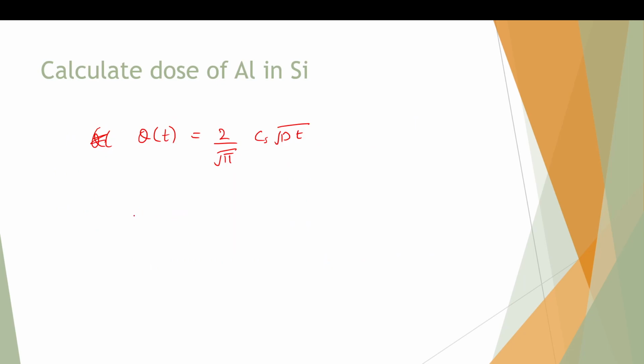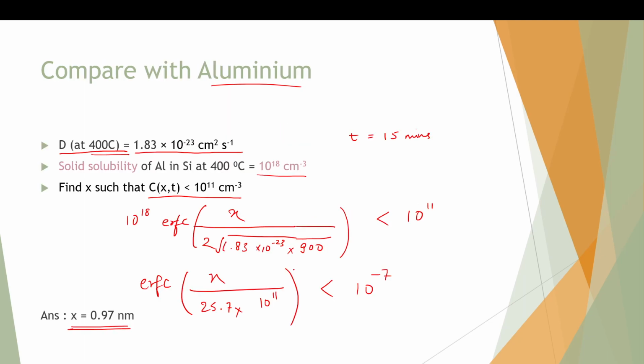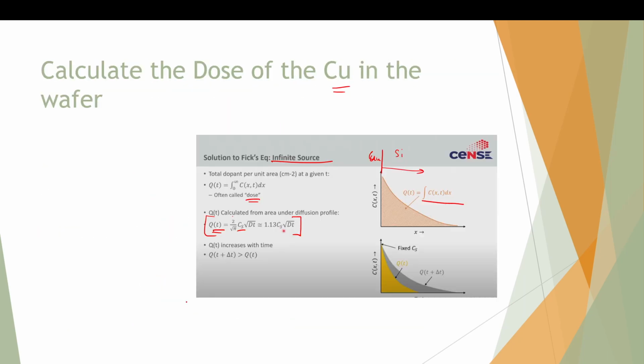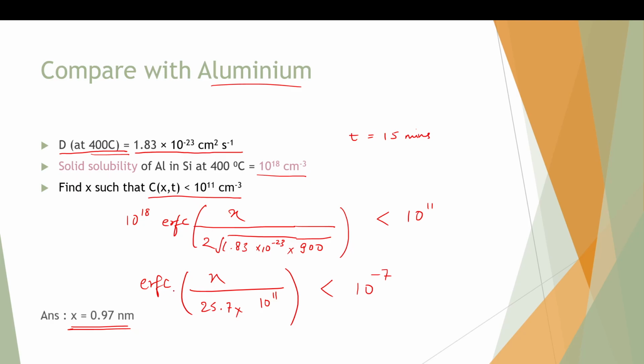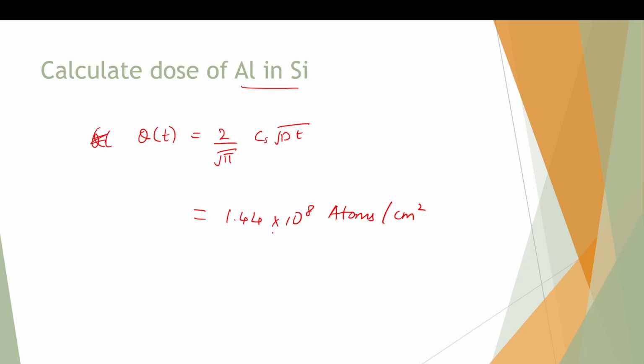The expected answer I can tell you right now: 1.44 into 10 power 8 atoms per centimeter square. If you compare this with the previous dose that we found, we did not do the calculation, but the dose we are supposed to find is 10 power 11 per centimeter square for copper, whereas for aluminium it comes out to be 10 power 8. So it is significantly lower, 3 or 4 orders of magnitude lower for aluminium.